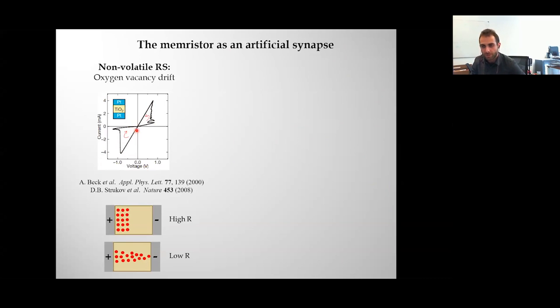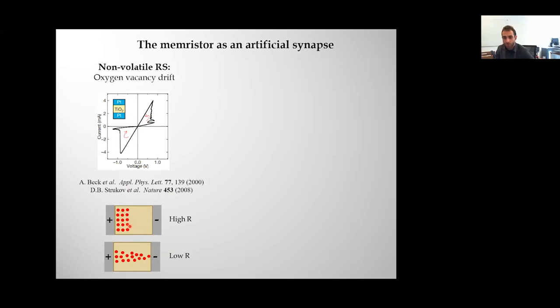And this is observed in different kinds of systems, but the ones that have been most widely reported are just transition metal oxides that are sandwiched between two electrodes. The idea is that you have oxygen vacancies, represented here by these red dots, within an oxide matrix, which is this brown area here. If you apply a strong electric field, you can actually move these oxygen vacancies, which are possibly charged, and you can make them form a filament that percolates between the electrodes, and that way you can change the resistance of your device.